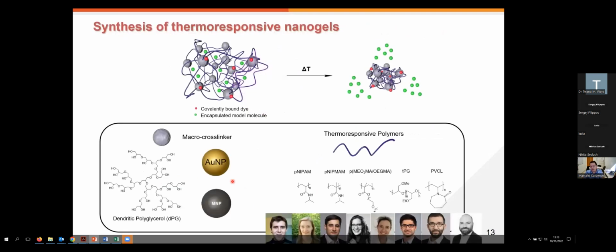Here, since we wanted to work with thermoresponsive materials and confine the size to diameters around 100 to 200 nanometers, we got excited about working with nanogels, or these cross-linked materials, where we use different sorts of polymers or small cross-linkers as cross-linking points. Here I'm illustrating, for instance, dendritic polyglycerol or hyperbranched polyglycerol as a cross-linker, but we have also used bisacrylamide and other popular cross-linkers. We also use inorganic materials as cross-linkers to induce other sorts of responses in the systems. But let's just focus on the temperature here.